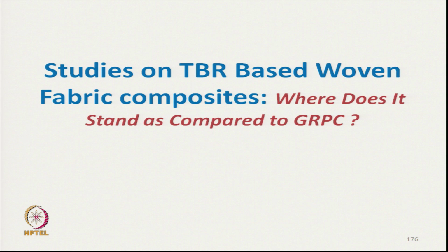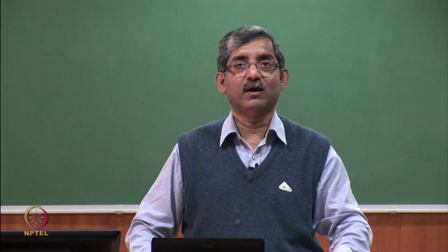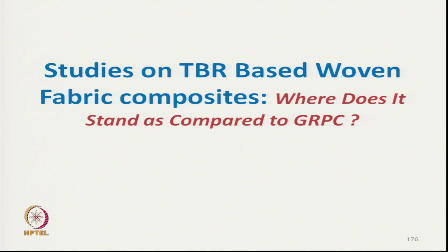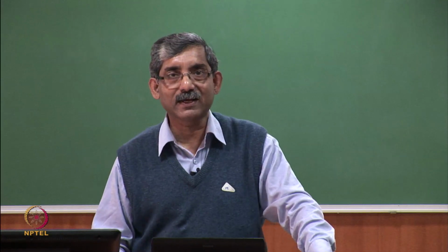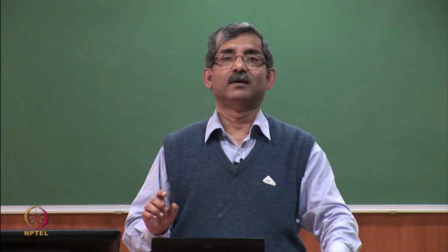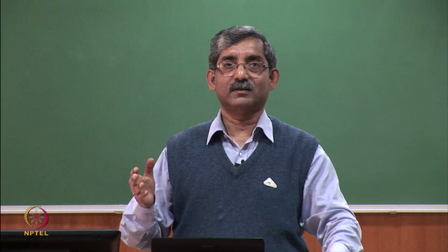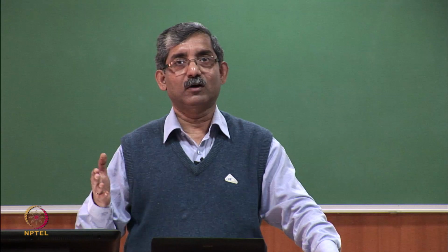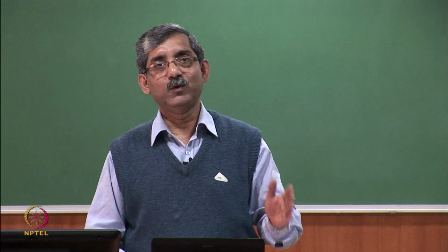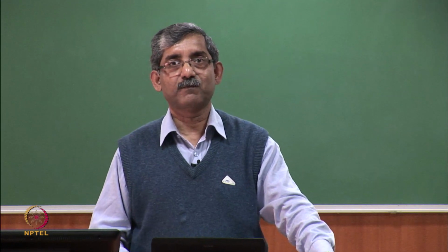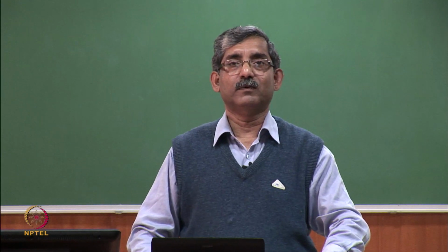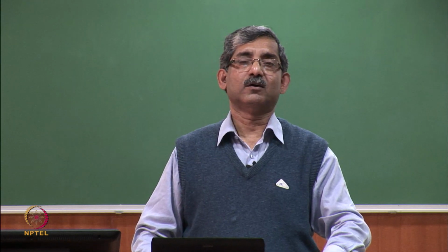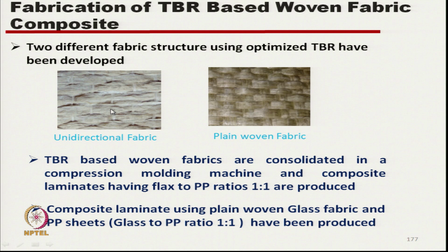Next study was the woven fabric we have developed, the plain woven fabric. After making the woven fabric we developed composites by film stacking technique, and the characteristics of this composite were compared with the unidirectional composite as just discussed, and also, for reference, we have taken the glass fiber reinforced composite. What we have done? We have developed unidirectional fabric and plain fabric.